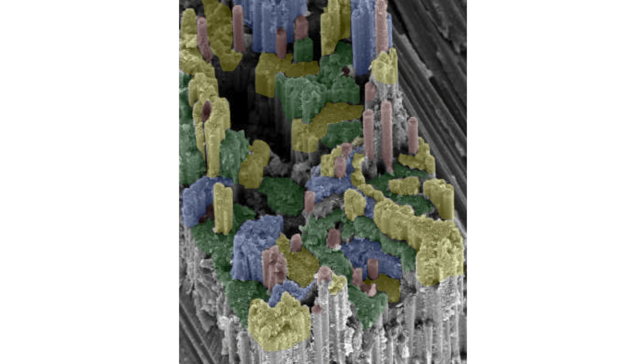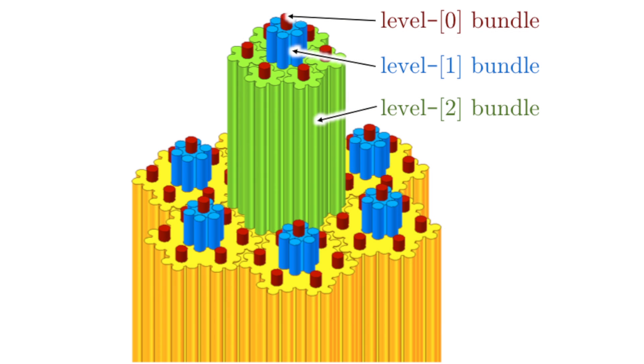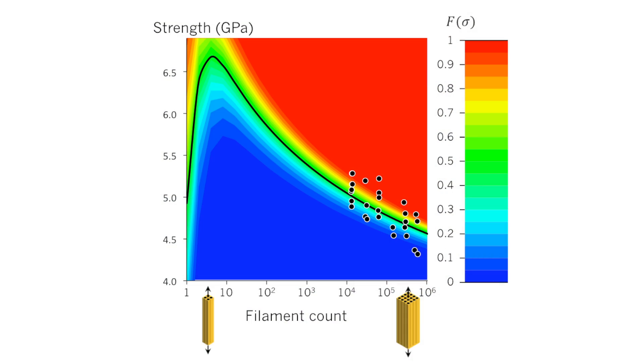The physical processes that lead to the fiber tensile failure mode in laminated composites are perhaps the most complex. While failure of individual fibers does not imply ultimate failure of the structure, individual fiber breaks accumulate in small clusters, and when these clusters reach a critical size, ultimate failure does occur and is typically catastrophic. Our main contribution in this field has been to develop the first analytical hierarchical model for the fiber tensile failure mode. This model idealizes the composite hierarchically — bundles of fibers composed of sub-bundles, which in turn are composed of further sub-bundles. Starting with the stochastic strength distribution for each fiber and the load transfer mechanism between fibers and bundles, the model predicts recursively the strength distribution for larger and larger bundles of fibers.